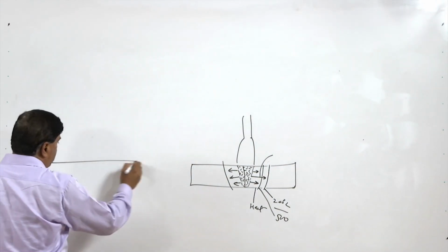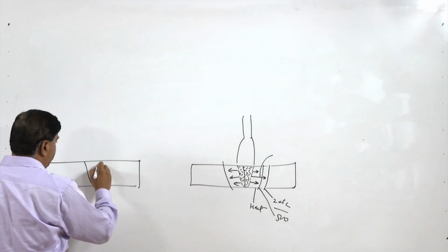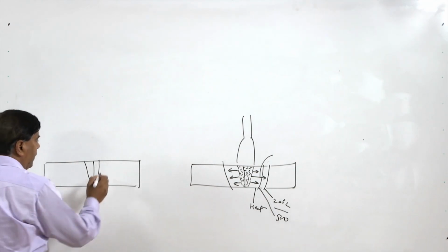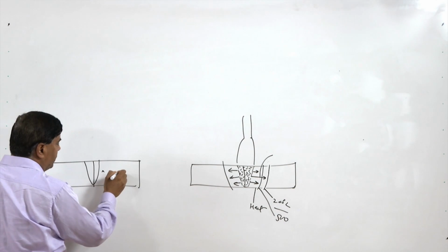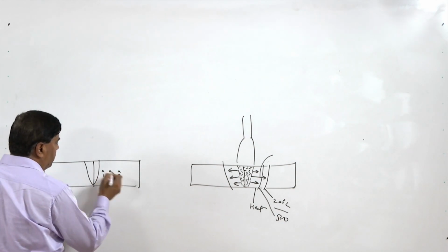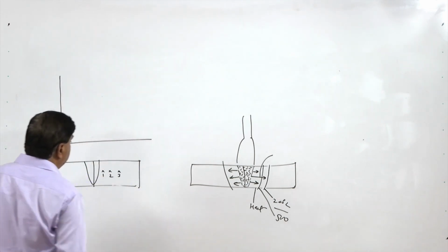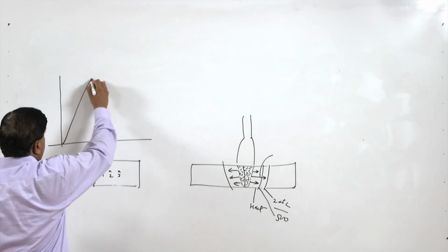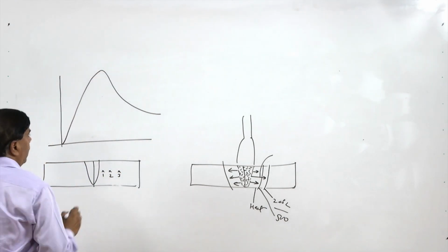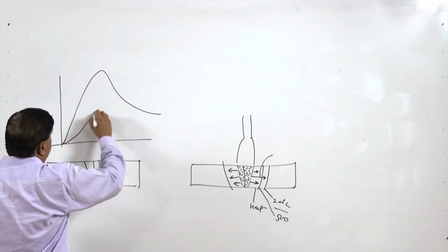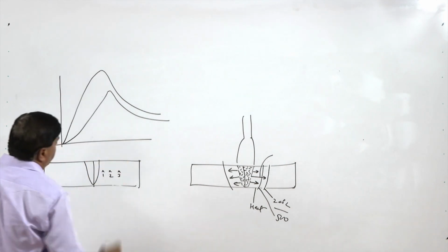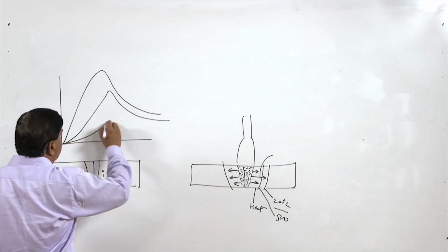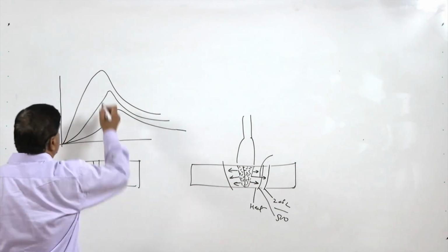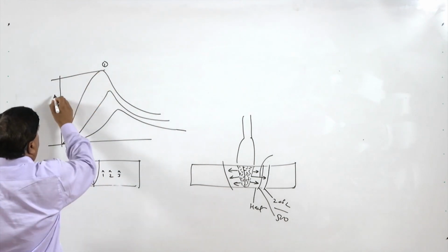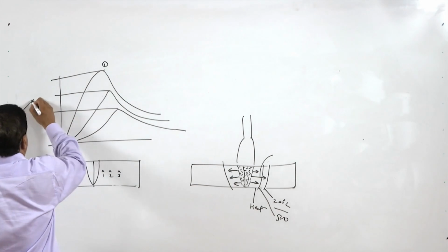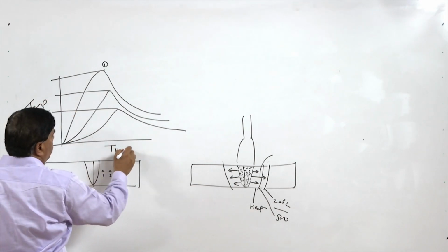Further, we know that whenever heat is applied, fusion will occur at the faying surfaces. If we take 3 points away from the fusion boundary, point 1, point 2 and point 3, each point will experience a different weld thermal cycle. Point 1 will experience the higher peak temperature and higher cooling rates, point 2 somewhat lower peak temperature and lower cooling rates, and point 3 still lower peak temperatures and lower cooling rates. Here, this is the peak temperature for point 1, for point 2, and for point 3. On the y axis we have temperature, on the x axis we have time.